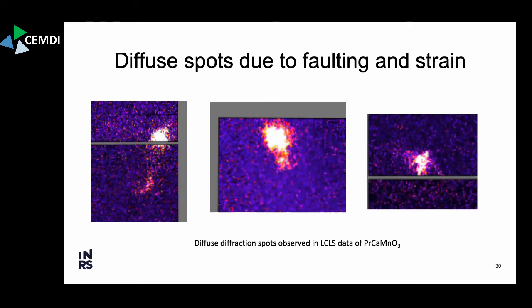And this works well when your spots are small and sharp, but it doesn't work well when you have more diffuse spots. And here, these are spots that are coming from a sample of PCMO that I collected at LCLS. And these are obviously extending more than just a few pixels. So your window has to be larger to properly accommodate for these. But then you begin to get into a very philosophical question of what is a spot actually? Is this one, or is this three, and how do you identify what is the useful information in this spot?